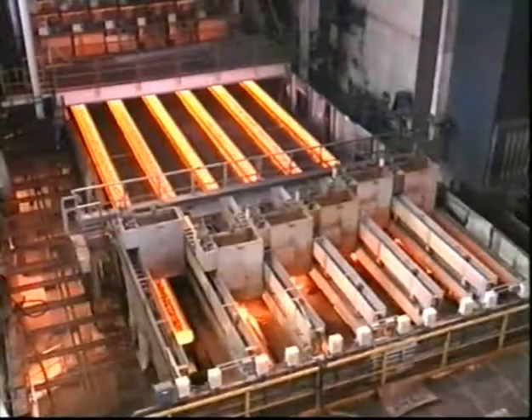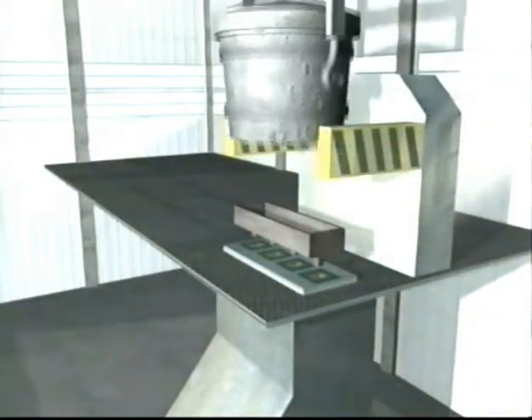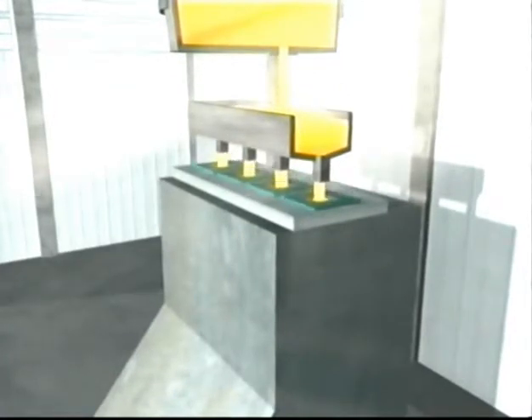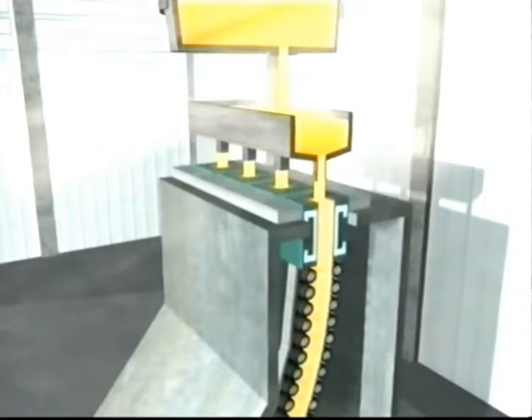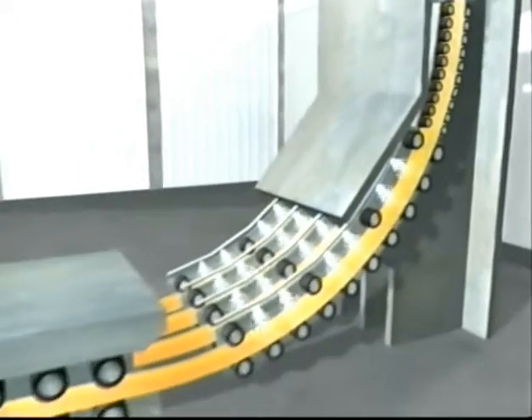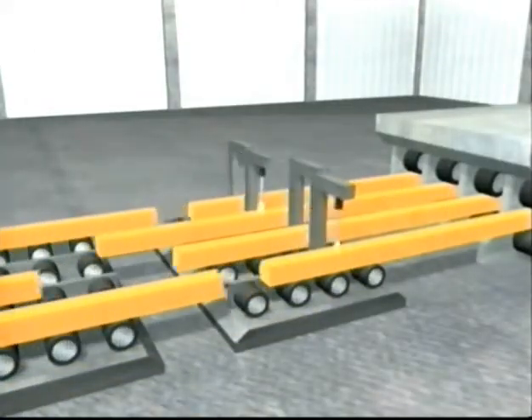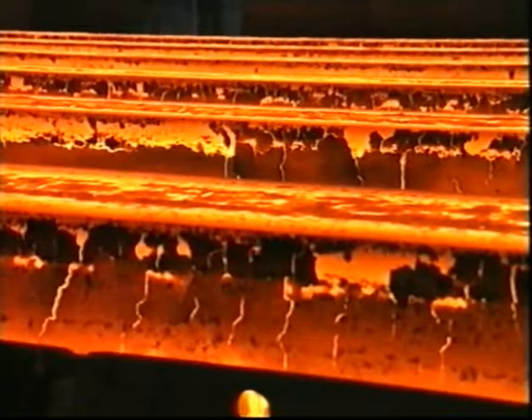Continuous casting is the process used to solidify the molten steel ready for shaping. A ladle of steel is teemed or poured through a gas-tight refractory tube into a tundish. This is a reservoir and feeds the steel through further gas-tight refractory tubes into a number of water-cooled copper moulds. The flow rate is controlled and, with only the outer shell solidified, the steel is drawn from the bottom of the mould through a curved arrangement of support rolls and water sprays. It then emerges horizontally as solid steel strands and is cut to length by automatic gas burners. Depending on their size, these solid shapes are called billets, blooms and slabs and are now ready for shaping into finished products.